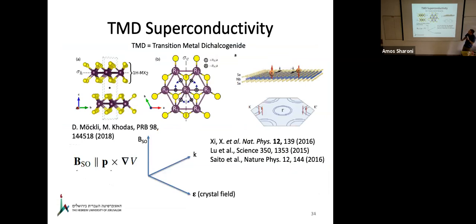why. And I'm going to say a few words about these transition metal dichalcogenide superconductors. It's a very, very hot topic today. Many people study them because these materials have a very strong spin orbit term. The result of this very strong spin orbit term is that electrons which propagate within niobium diselenide experience an effective magnetic field which locks the spins out of the plane. This means that if you look at a superconductor which has Cooper pairs, you have a spin orbit coupling which very strongly stabilizes the Cooper pairs.